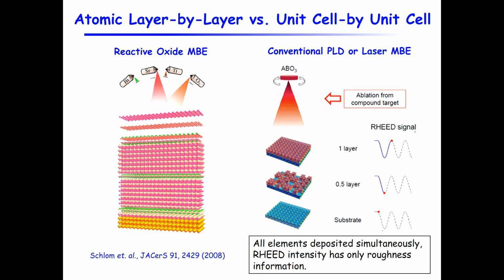You monitor the oscillation that reflects the roughness of the surface. When you have half a unit cell grown, the surface is rough, so the RHEED intensity goes to a minimum. And when you completely cover one layer, it becomes smoother, and the intensity goes to the top. As a matter of fact, the RHEED intensity reflects both roughness information as well as chemical information, because of different scattering cross-sections. But in this case, of course, all your elements come together, so that averages out the information due to different elements.